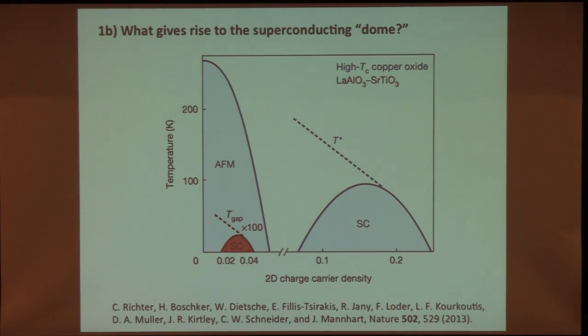And so not only is there considerable data that this goes on in the cuprates, this is a sketch of the phase diagram of the cuprates showing some scale which is really a zero temperature scale. This is some sketch of what the zero temperature gap scale is. But here is for some other very low electron density, strongly correlated 2-dimensional superconductor that occurs in some heterostructure of transition metal oxides. And again, what you see is a superconducting dome where the temperature scale inferred by measuring the zero temperature gap rises as the superconducting Tc drops as the concentration of mobile carriers gets lower. So this is a very general, I mean, this Tc is 100 times lower. This isn't a high temperature superconductor, but it's the same drama.